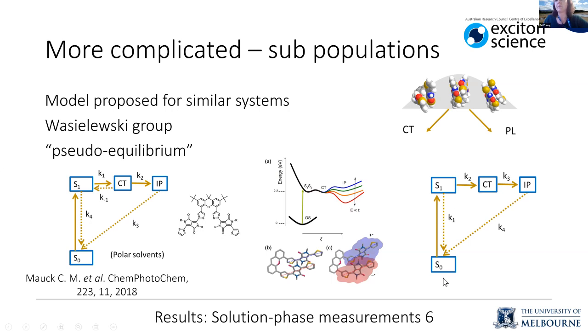What I think is happening, and what I'm trying to model at the moment, is a system where we actually have a population of chromophores here. And those chromophores have different conformations where they are different distances from each other. And so the ones that are quite far apart probably act like monomers and just have normal monomer fluorescence. But the ones that are close enough together can have this charge transfer process happen and can follow that second pathway. So I'm modeling it with a bridged system where the molecules in the excited state can either take one pathway or the other, depending on what conformation they have. And that's a work in progress.